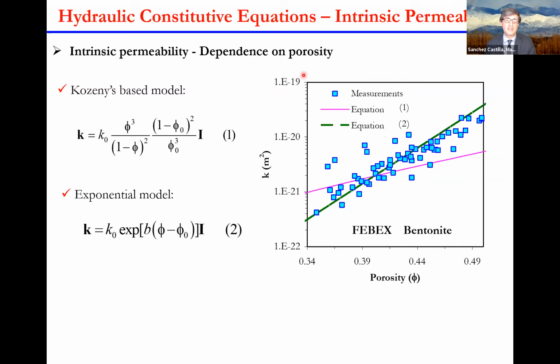And you can see that the permeability that is here in this vertical axis depends strongly on the porosity of our compacted clay in this case, and we need to develop an equation. This is based on the Kozeny model, and this is one exponential law that allows us to basically track how the permeability will change with porosity.